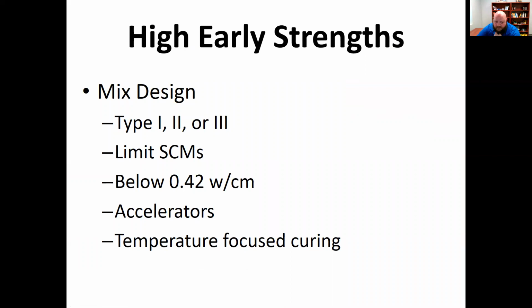So high early age strength mixes, they can use type 1 or type 2. A lot of times I'll see a type 3 mix. So type 1 or type 3 is really common to get that initial gain. You may even take out your SCMs because they don't help out as much in the beginning. And typically you're going to be, again, below a 0.42. You're going to see a lot of times accelerators being used. You may even see a type 3 and an accelerator and not very many SCMs. It just depends on what you're trying to do and what performance criteria you're trying to have. And then you also have your temperature focused curing. So, like applying heat, for prestress facilities, they can apply heat to the beams to really increase the reaction between the cement and the water and that accelerator.